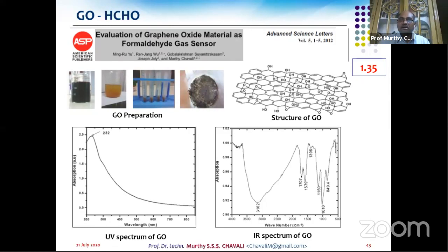And again, with the increase in research potential on the development of graphene, we started to develop this by using Hummers method. But unfortunately, due to the lack of an inert atmosphere, we ended up with graphene oxide material. But there we had some industry problems. They wanted to measure formaldehyde. So instead of graphene material, we used the graphene oxide material for developing a formaldehyde gas sensor.